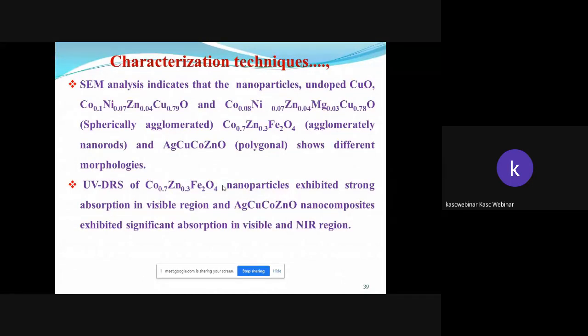UV-DRS, that is diffuse reflectance spectroscopy, of doped ferrite nanoparticles exhibited strong absorption in the visible region, and doped zinc oxide nanoparticles exhibited significant absorption in the visible and near infrared region.